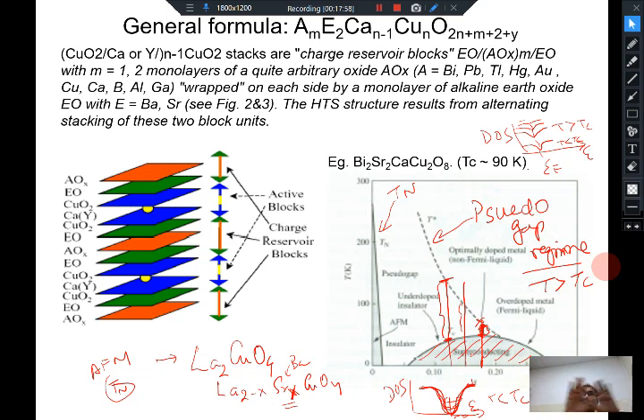You know that a superconducting state is a macroscopic quantum state where the entire system behaves in unison. Everything is in phase. Here in the pseudo gap regime, one believes that there are microscopic superconducting puddles which are not having identical phase. They have some sort of pairing, a weak pairing which can survive up to pretty high temperatures, but this puddle is not correlated with this puddle. These puddles are behaving separately from each other. They have different phases from each other, but microscopically you still have some superconductivity remaining in this region.